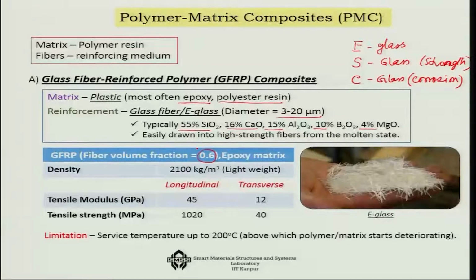What is the kind of weightage possible? By weightage, what do you mean? What is the maximum fiber volume fraction possible? That is generally 0.6. That means 60% volume will be fiber at maximum. You always try to increase the amount of fiber in order to improve the strength, modulus of elasticity, etc. So 60% is generally the maximum possible, and 40% then is the epoxy matrix. With that composition, the density will come to about 2100 kg per meter cube. Just compare that with the density of steel, which is about 7400 kg per meter cube.